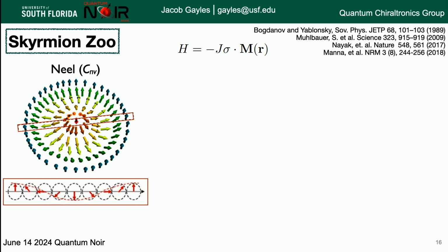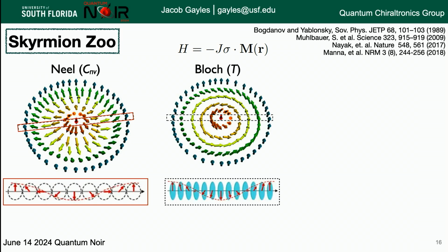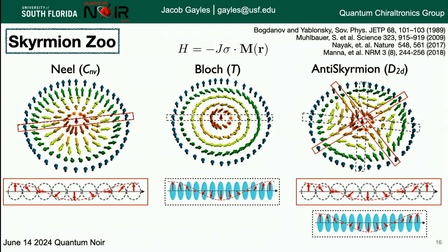If I take a line here, this gives me one of these Néel domain walls. And there's another type of skyrmion, but it has the same topology. This is called a Bloch skyrmion. So this one, if you look at the domain wall here, it rotates in and out of the board, where this one stays in the board. And then lastly, you have what's called an anti-skyrmion, which is a mixture of the two. And this one actually winds in the opposite direction, meaning that the topological charge actually changes in this one.